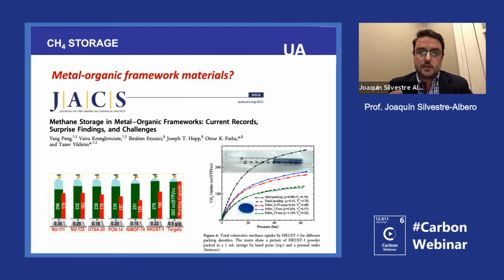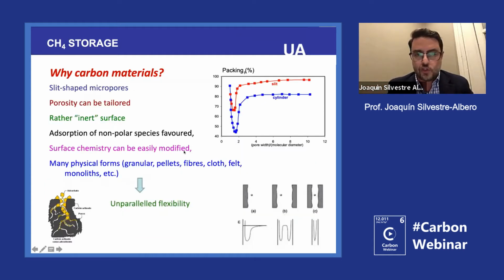That means that these types of MOFs, which are extremely good for natural gas, at least some of them, have mechanical instability. And as you can see here, only by pressing the MOF, you are able to break it. So that was a big limitation if you want to prepare, for instance, a monolith. So immediately we were thinking, okay, this is an advantage of carbon. Carbon is very rigid. We can apply pressure, and it's very difficult to break the structure.